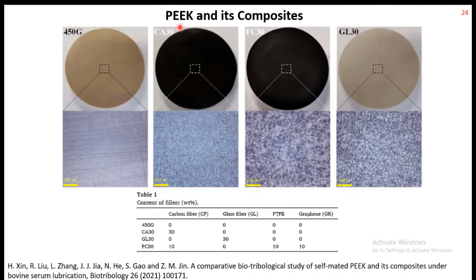Other type of combination: we have PEEK and its composites. Some researchers have started working on PEEK, polyether ether ketone, as a replacement for UHMWPE. PEEK is a very good engineering material - it has better mechanical strength compared to UHMWPE, almost double, and better creep resistance as well. But tribologically, PEEK is not a very good material compared to UHMWPE. It gives slightly higher friction, and wear is also high in the dry case.